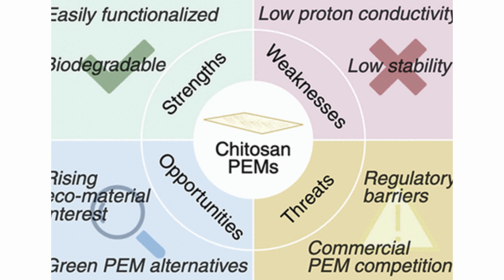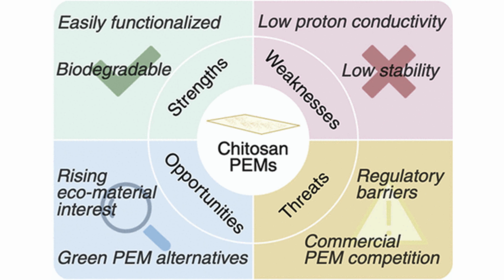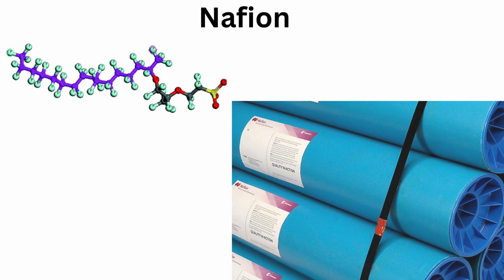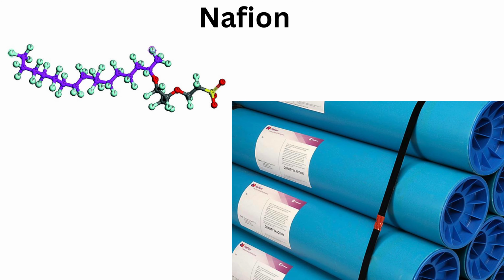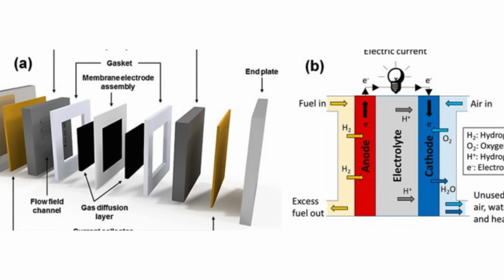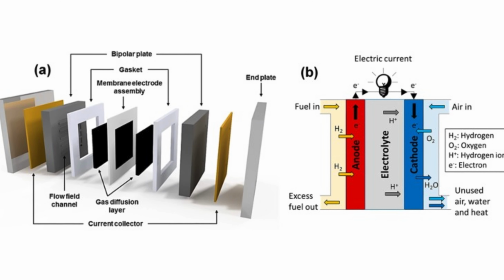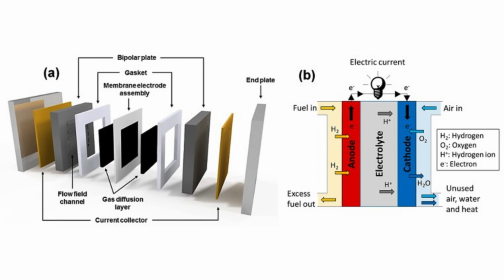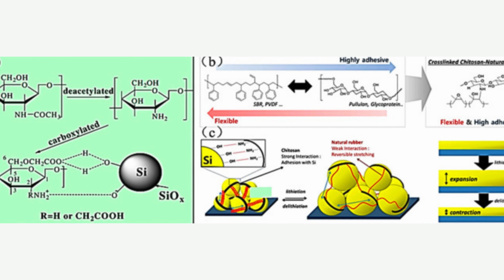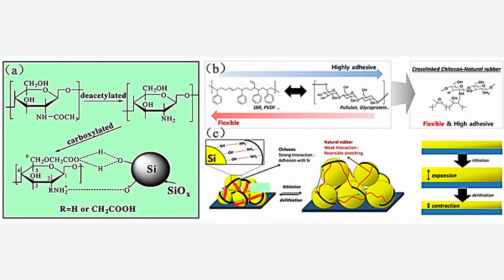Energy and electronics: toward biodegradable components. Proton exchange membranes, PEM. Sulfonated, phosphorylated chitosan, often with nanofillers or ionic liquids, is emerging as a bio-based alternative to Nafion for low-temperature fuel cells. Recent 2024 to 2025 reviews report conductivity gains and better high-humidity performance, while durability and oxidative stability remain the gating factors. Battery binders. Chitosan is a water-processable, mechanically dissipative binder for silicon and silicon-graphite anodes.